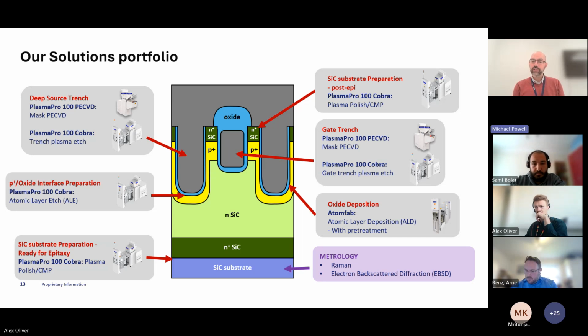And we have a range of technologies that allow you to look at each individual layer and have an ability to control each individual layer. And then, if we go back to the other divisions of OI, we can use Raman and we can use electron backscatter diffraction to actually tell you about the quality of the initial silicon carbide as well. So we can go through the entire methodology of producing the silicon carbide device, and we have a solution for each layer. Next slide, please.